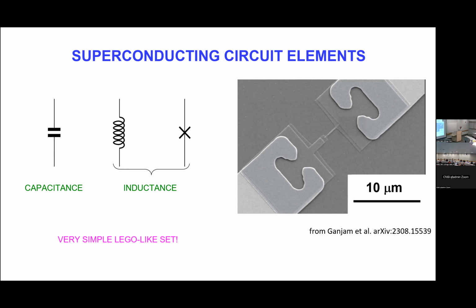So you are happy that the coherence length, or equivalently the diameter of Cooper pairs, is very large in aluminum. We know that the superconductor has a perfect gap, so there's no density of states in the gap in the superconductor. That's very good for dissipation. Then there are two other miracles for aluminum.